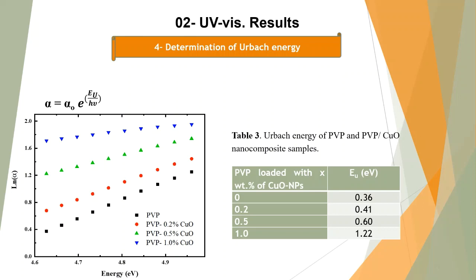As we can see from the table, increasing the concentration of copper oxide leads to an increase in the values of the Urbach energy. This causes an increase in the number of traps and a decrease in the visibility of energy transitions, which lowers the values of the optical band gap energy. According to Davis and Mott, the filling process caused more defect states to exist within the polymeric matrix, which is why the Urbach energy changed.